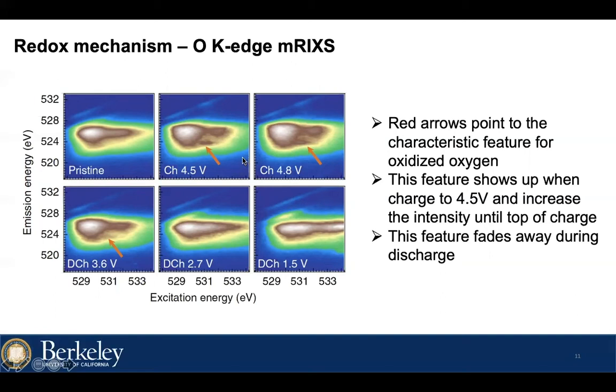And from the literature, we know that this feature pointed by the red arrows is a characteristic feature for oxidized oxygen in the lattice. We can see this feature does not exist in the pristine sample, but we can observe it when it's charged to 4.5 volts, indicating the oxygen redox starts around this voltage. And the intensity keeps increasing when further charged to 4.8 volts, indicating more oxygen anions are oxidized. After that, during the discharge process, the intensity of this feature gradually decreases, and you can still observe it with low intensity when discharged to 3.6 volts. But when you further discharge it, this feature totally disappears. This indicates the oxidized oxygen gets reduced to 2- during discharge, meaning a reversible oxygen redox process.